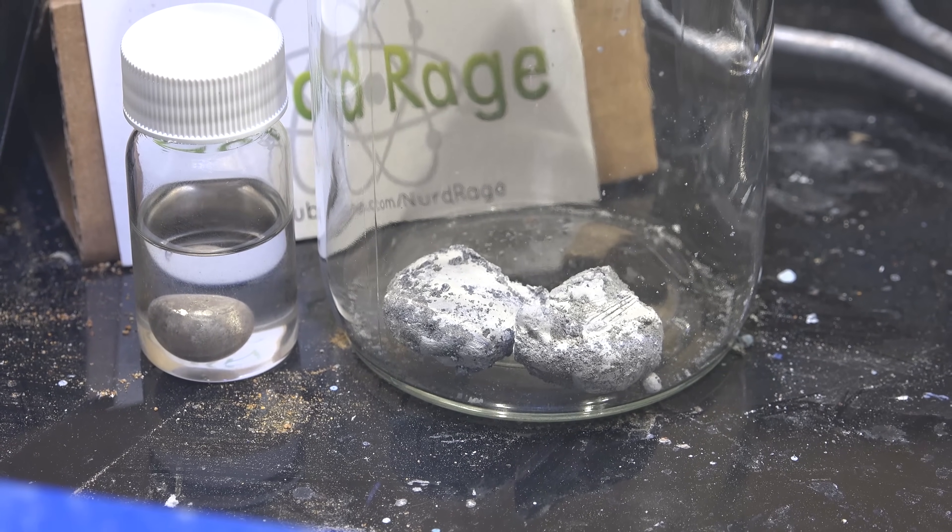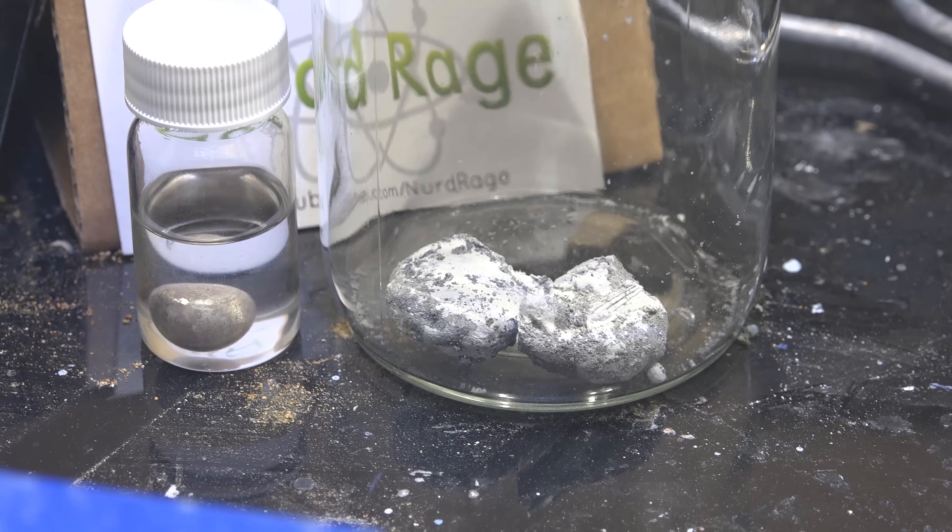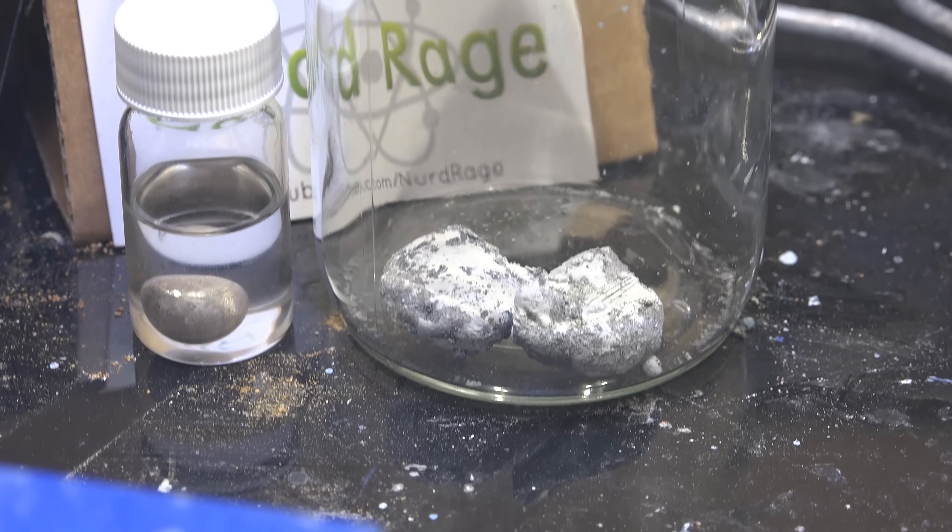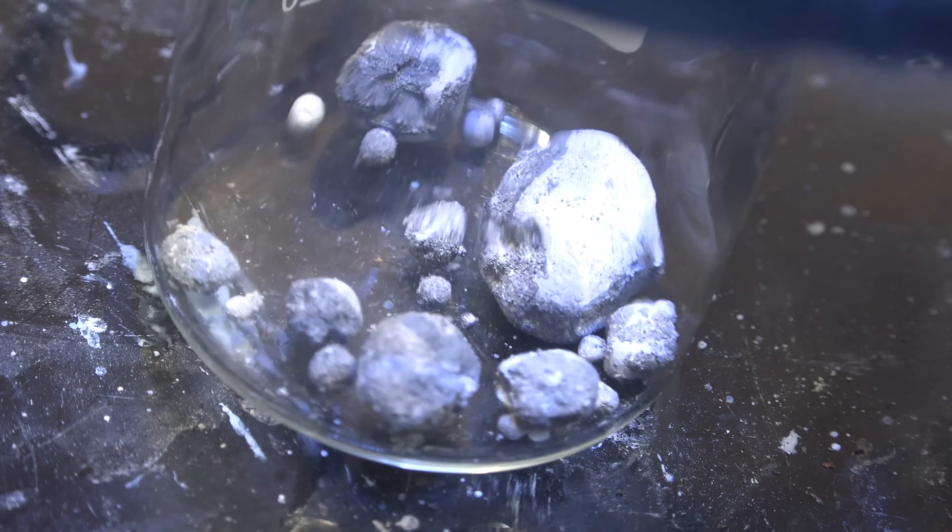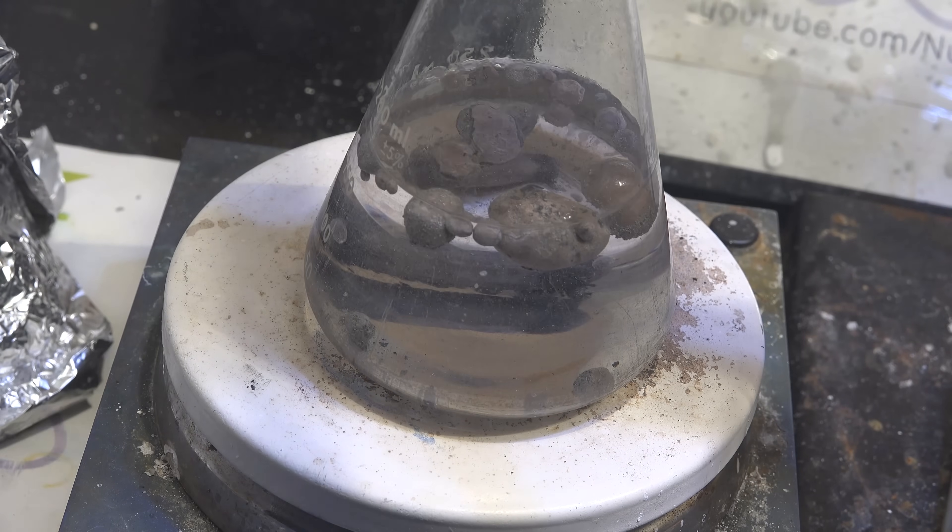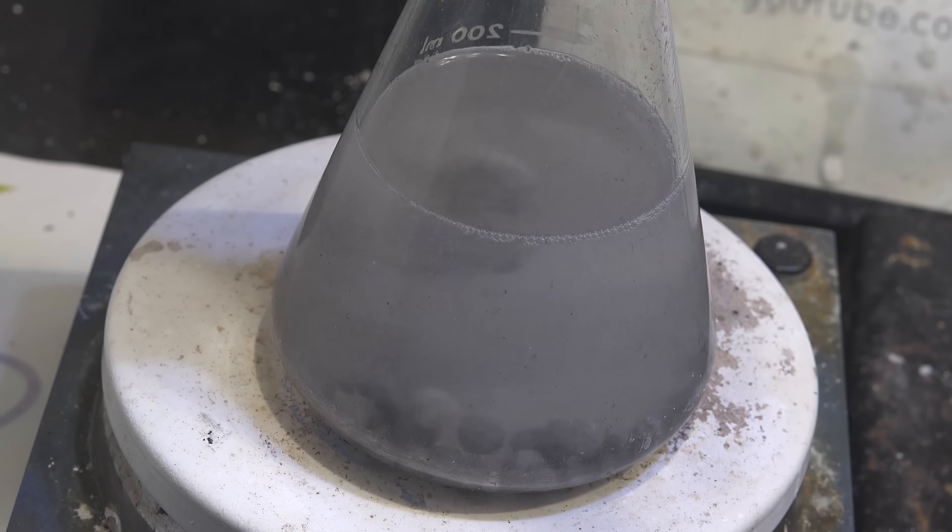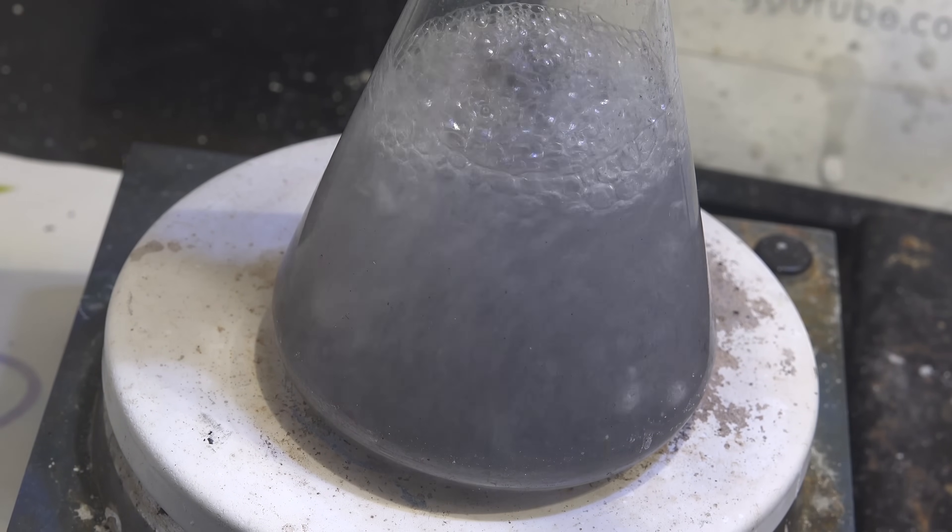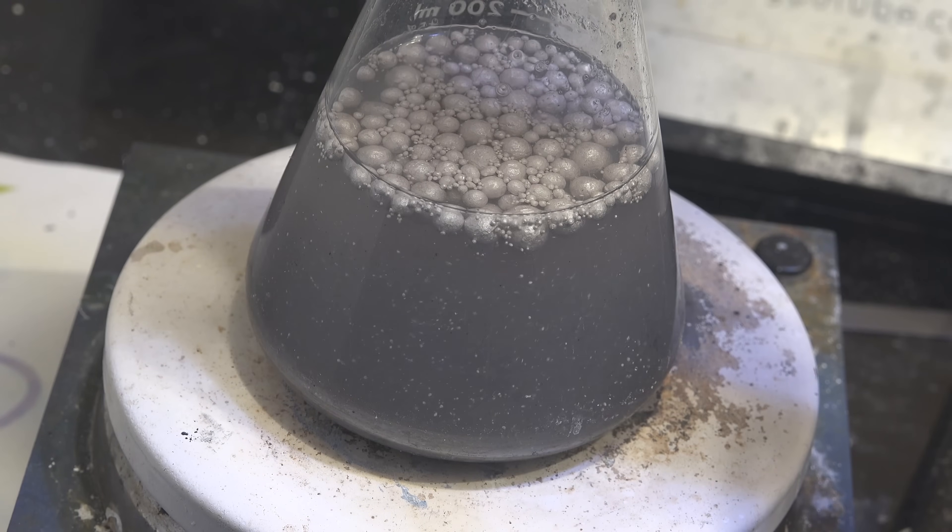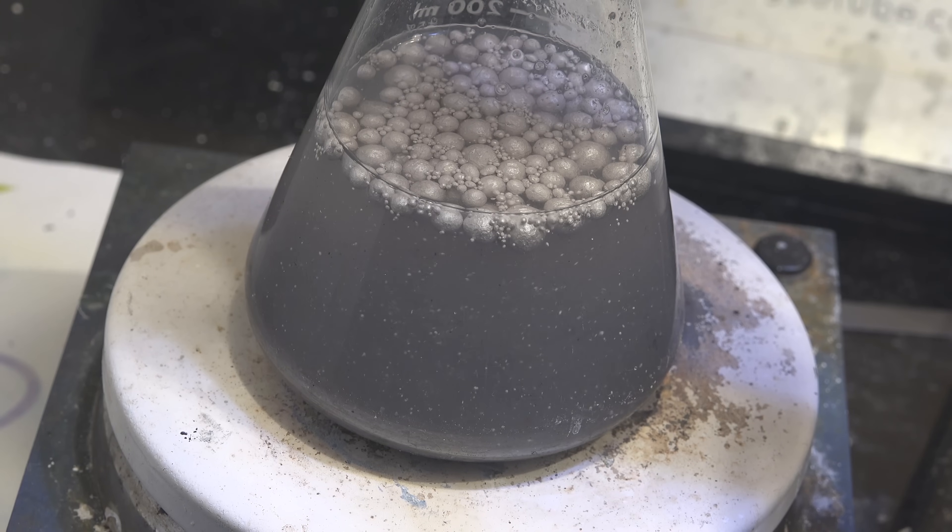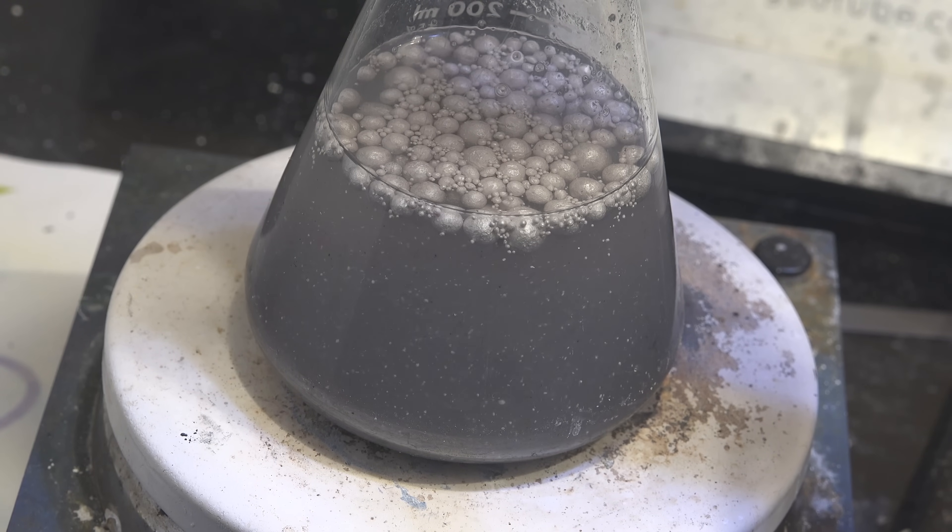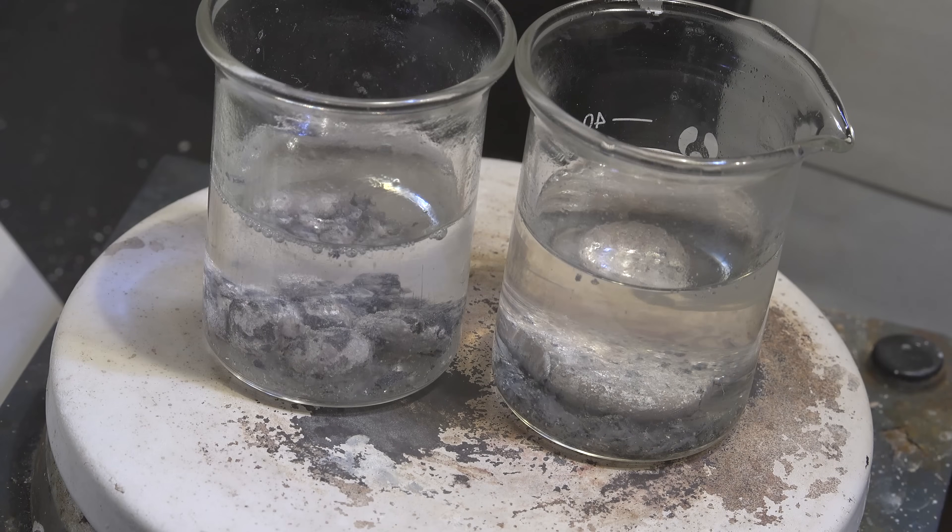Now if you don't want large spheres and actually want small spheres of sodium then the cleaning process is much simpler. First scrape off as much of the slag as possible by hand and then boil the sodium in dioxane. You can even stir the mixture to encourage the breakup of the sodium. This will produce smaller spheres of sodium. They're useful for reactions where you need large surface area. But aren't good for long term storage since larger surface area means they also decay faster as they react with air and moisture.